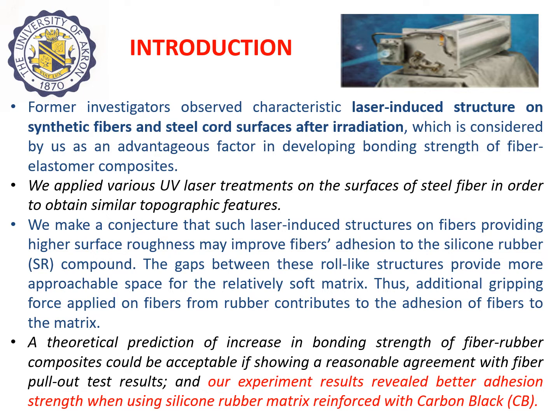A theoretical prediction of increase in bonding strength of fiber-rubber composites could be acceptable if showing a reasonable agreement with fiber pull-out test results. And our experimental results revealed better adhesion strength when using a silicone rubber matrix reinforced with carbon black.